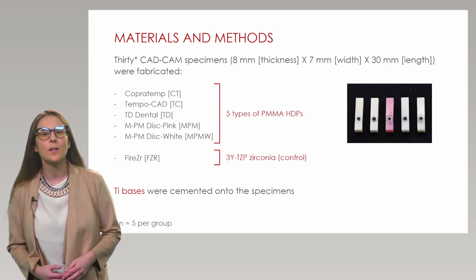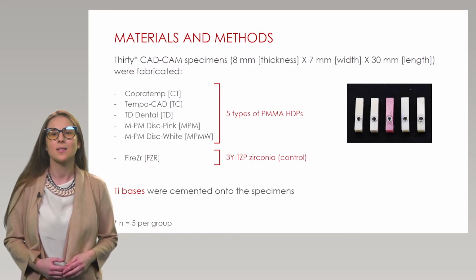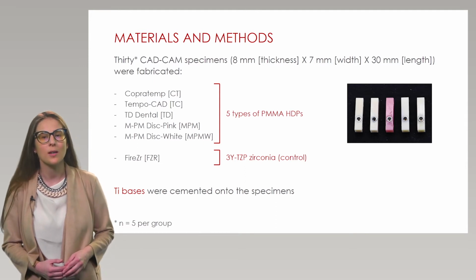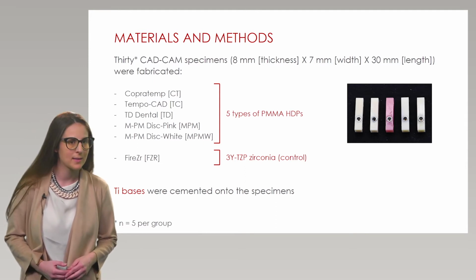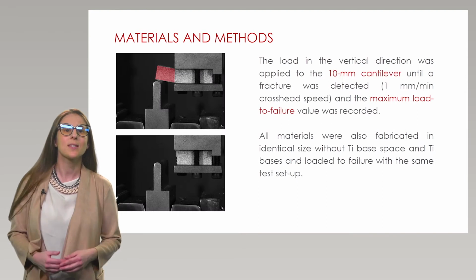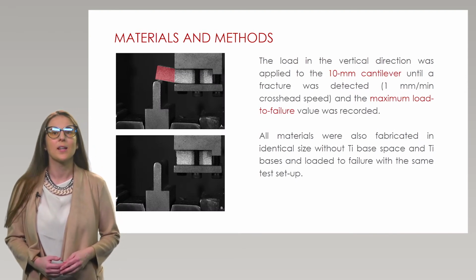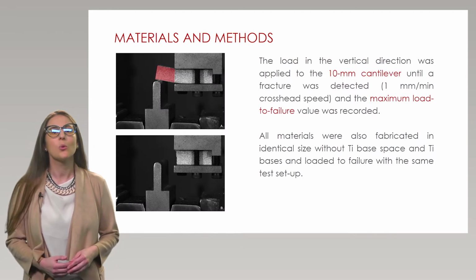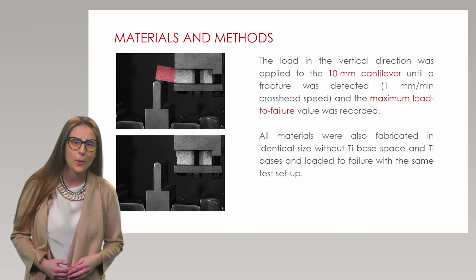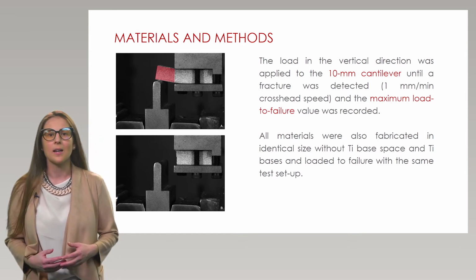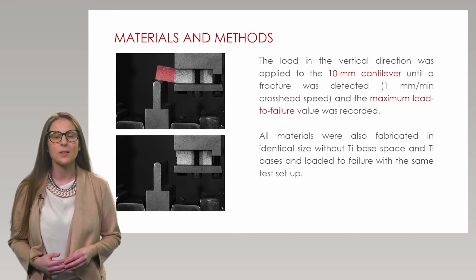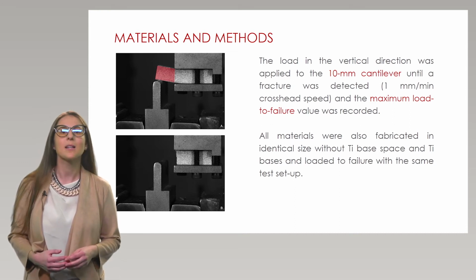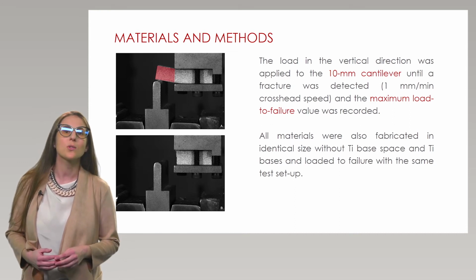So 5 different types of PMMA high-density polymers and 1 type of zirconia as control were produced and tested. Each sample was fixed in a universal test machine. A load in a vertical direction was applied, simulating a cantilever of 10 millimeters until a fracture was detected and the maximum load to failure value was recorded.